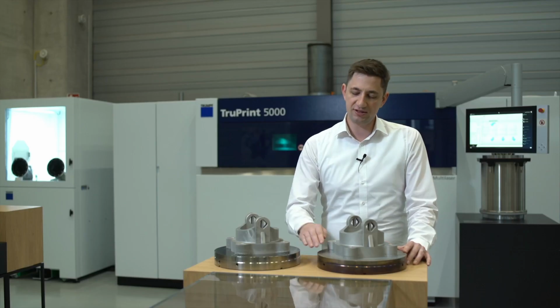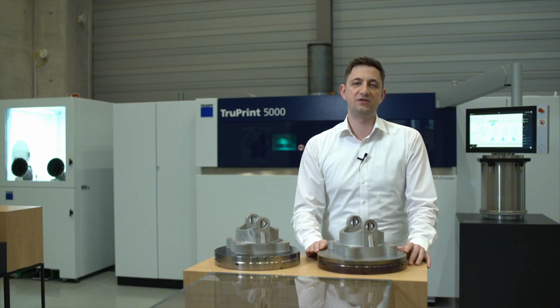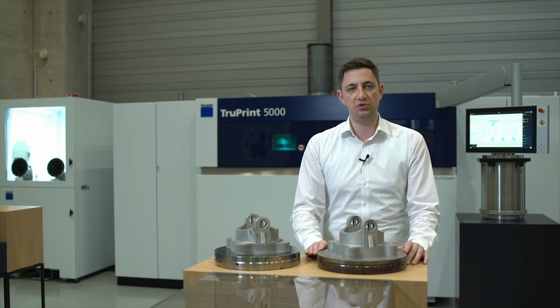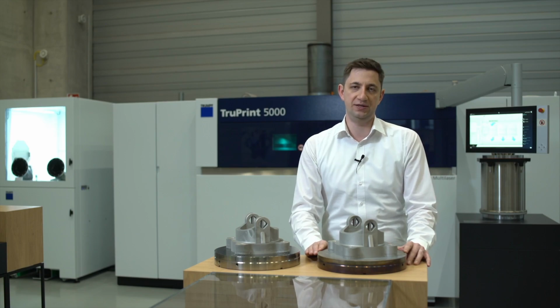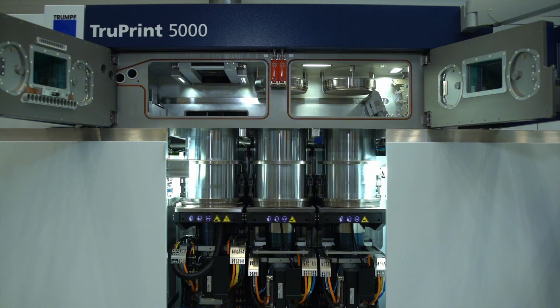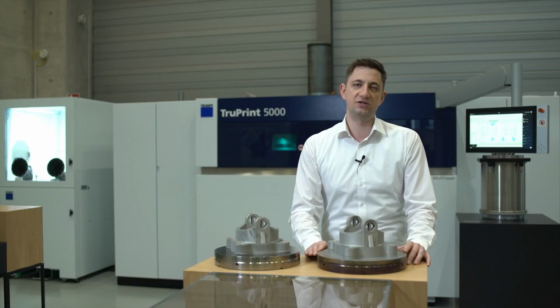Well, our round substrate plate certainly helps to achieve a homogeneous heat distribution compared to square substrate plates. But there's more to it. We used an improved cooling concept for axis, build chamber, and optical components to maintain positioning accuracies during the whole build job. Furthermore, we enabled the machine to get below 10 ppm in terms of allowable residual oxygen. That is especially important to avoid oxygen pickup by the processed materials.